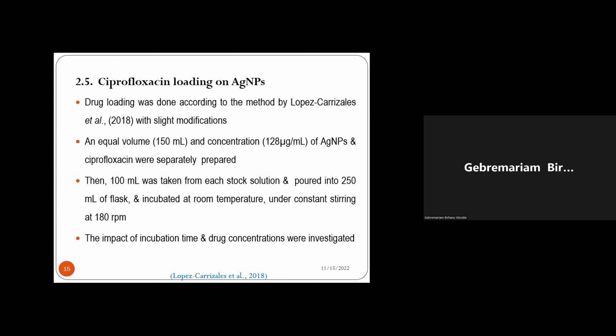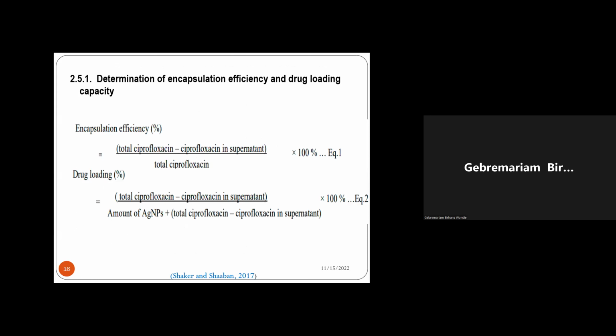Then ciprofloxacin was loaded on the silver nanoparticles after the optimum and maximum yield of silver nanoparticles was determined. We loaded ciprofloxacin on the silver nanoparticles. That was the major objective. So drug loading was done according to published methods with slight modification, following the method written here. And the drug encapsulation efficacy and the drug loading capacity of the nanoparticles were determined using the common formulas.